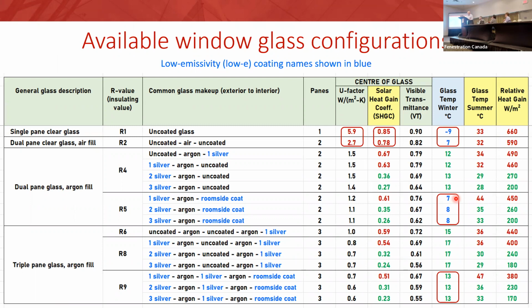So if you look at the products that don't have a room side coating, you'll see that the glass surface temperature is quite a bit warmer. They're all at around 12 or 13 degrees. And you'll notice that the R8 family, which I'll call the passive house glass family, is giving you a nice warm 17-degree room side temperature in this cold Chicago winter. When you add one more low-E coating, your glass temperature is back to where it was with a double pane unit, right? So again, is that a wise choice? Well, if you really want to have a slightly better R value from R8 to R9, knock yourself out.